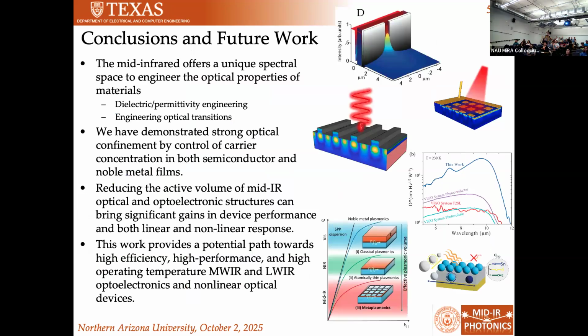I'll end by saying the mid-infrared, I think, offers a unique spectral range to engineer optical properties of materials. You can engineer the dielectric, you can engineer permittivity. I showed you a bunch of different ways of doing that, either by changing the material response or by patterning the material. And we've shown strong confinement of optical light, either by carrier concentration in semiconductor and noble metal films. We've shown that we can reduce the active volume of our devices and structures, and actually realize gains in our device performance.